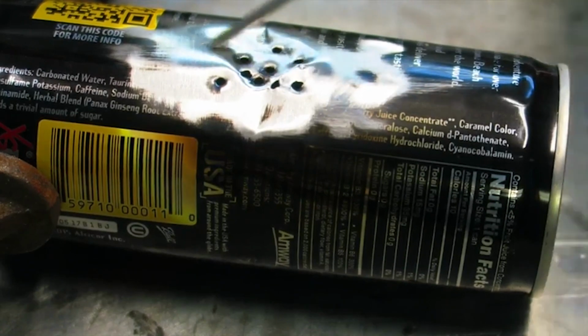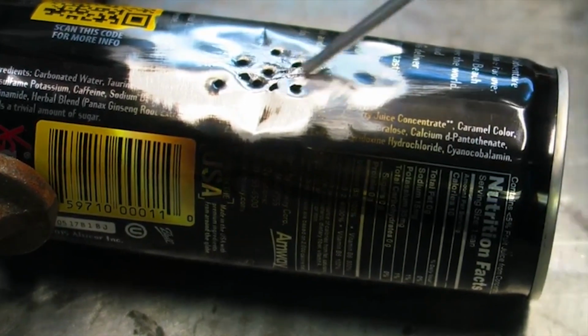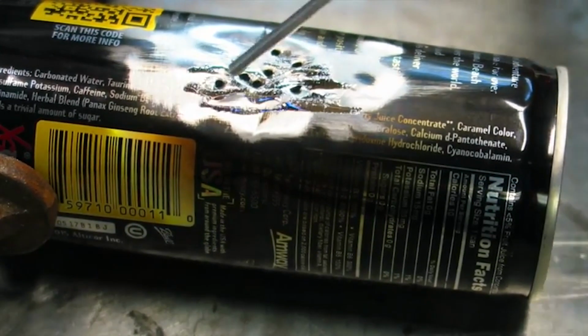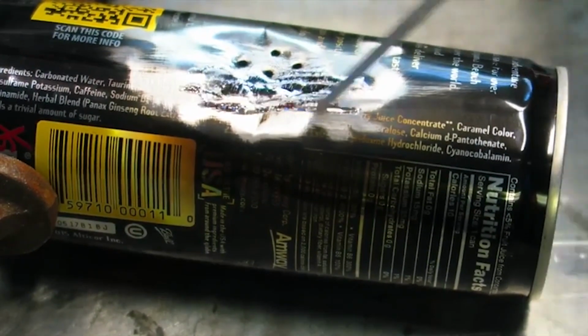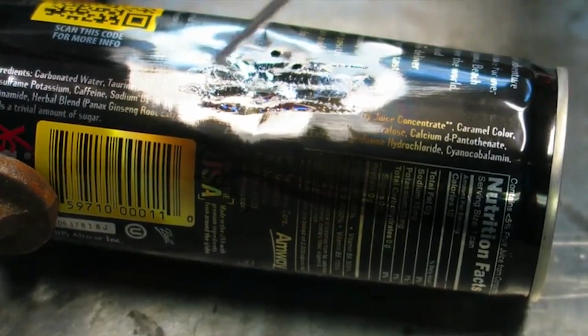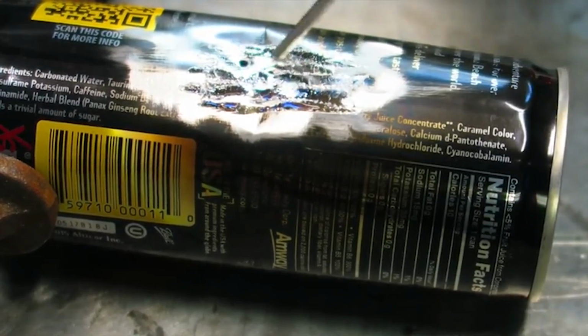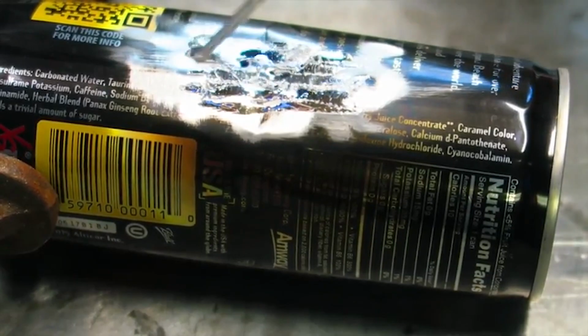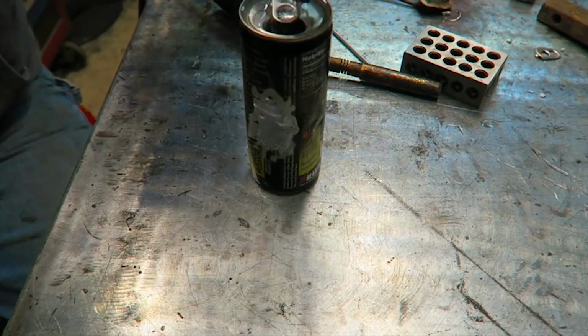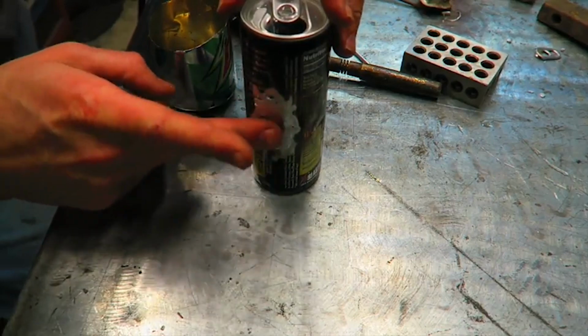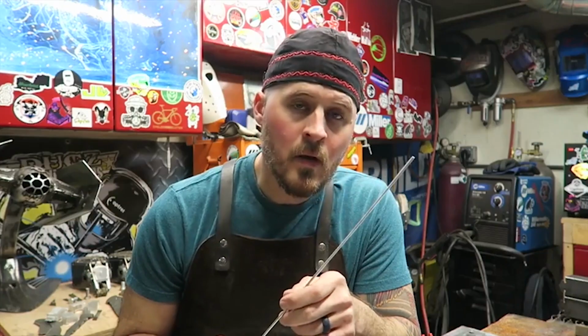Let's go one step further. Let's go one step thinner. Trying to repair the side of a thin aluminum can would be extremely difficult with a welding process. I've drilled several holes in this can to simulate holes in a thin aluminum tank of some sort. And as you can see, heating the base metal very carefully, the holes are very easy to repair in much the same fashion. And also, when the repair is done, that area of the tank is now reinforced. So it's a win-win.